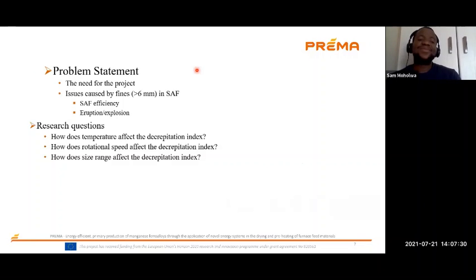One may ask, is there really a need to research this problem of decrepitation in a rotary kiln? Yes, there is a need. The way the SAF works, it doesn't work properly if it is fed fines. What I mean by fines, I mean particles that are less than 6 millimeters. So in this current process, the ore has been screened for particles that are less than -6, and we only feed particles that are more than 6 millimeters. Now, when you preheat this ore, a question arises: will this ore decrepitate? And if it decrepitates, how much of it will decrepitate? And what problems may we experience in the SAF if we feed these fines?